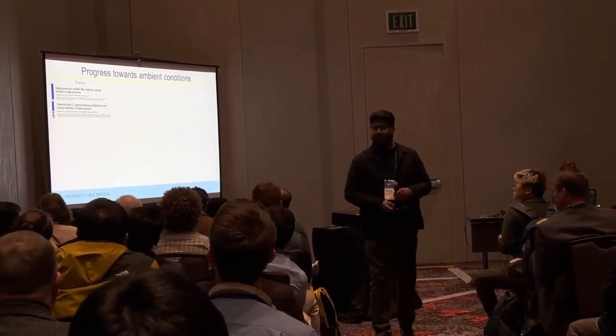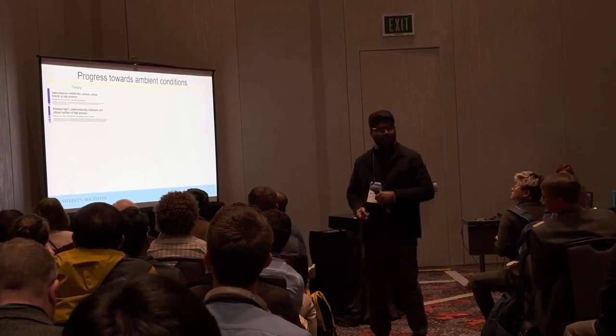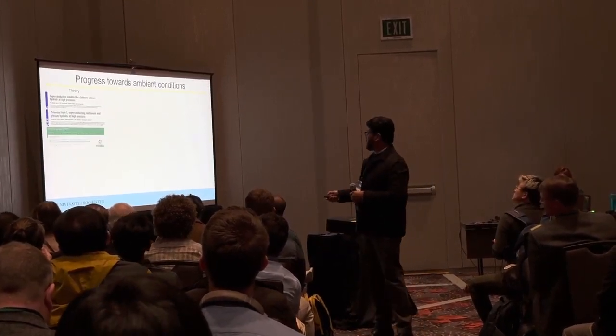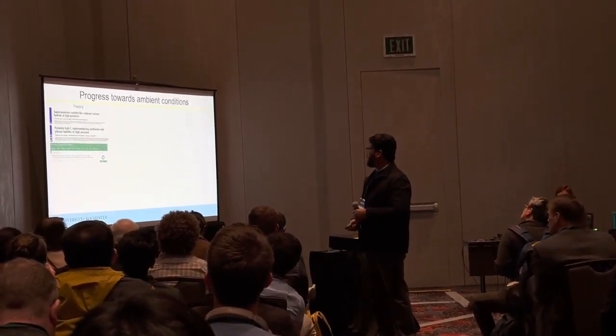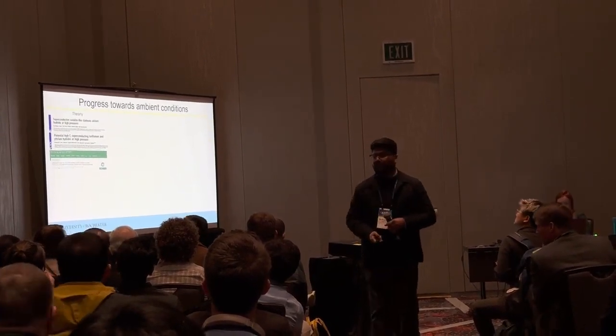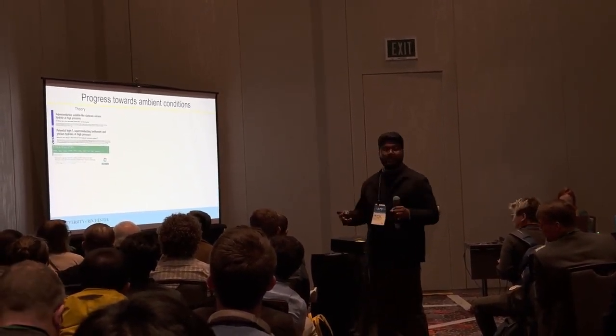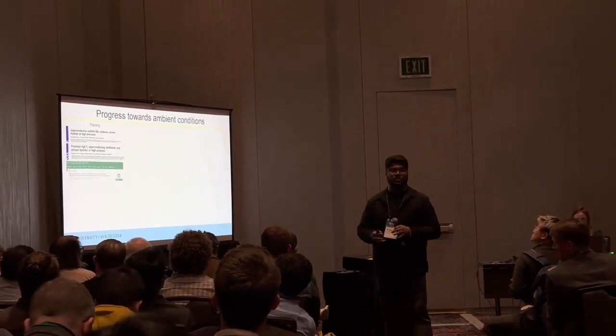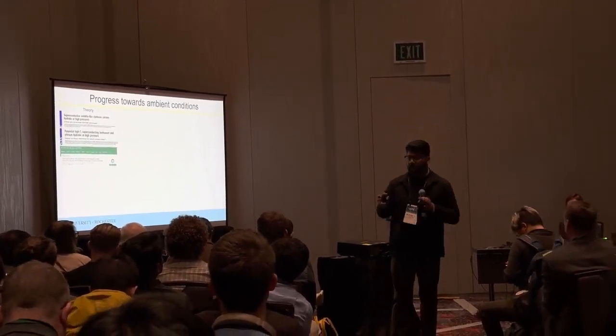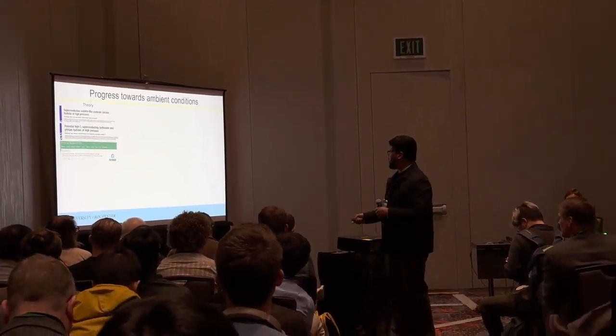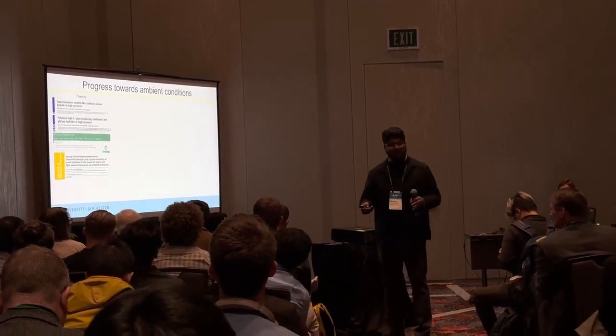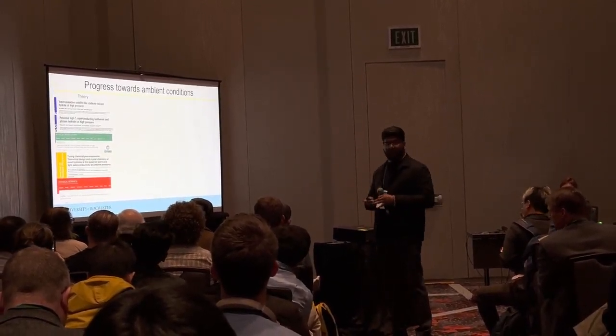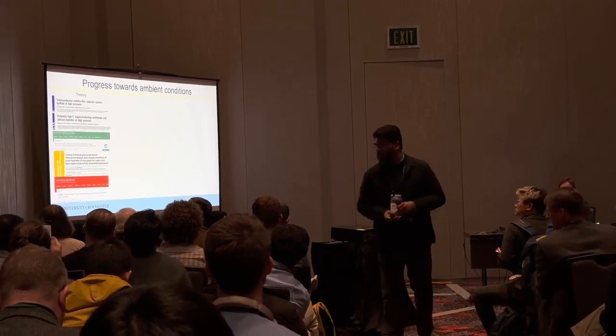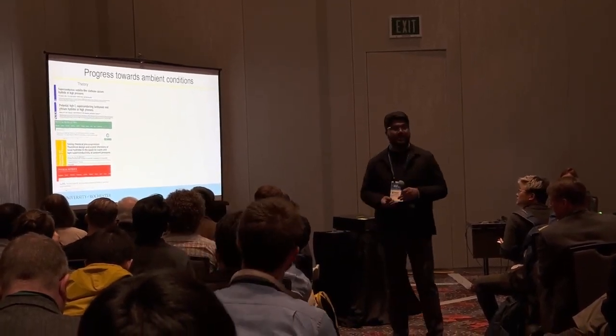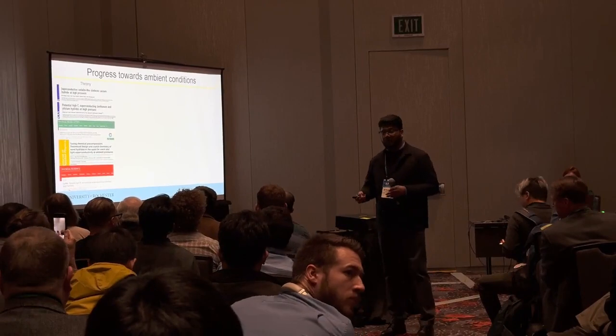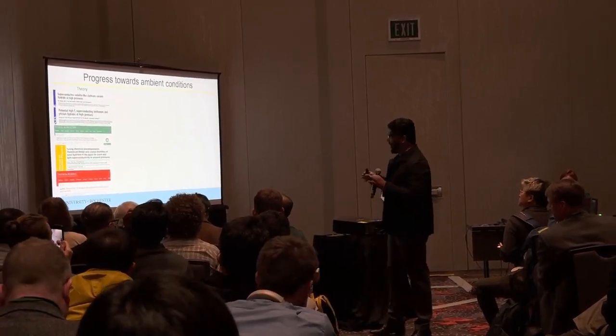And then later we see the lanthanum hydride and yttrium hydride from Russ Hemley's group, and very soon after that there was another prediction from the Cambridge group and the Yang group. Again, this rare earth metal hydride in solution to mimic the same hydrogen superconductivity at much lower pressures. Since then, there are a lot of theoretical works from the Zurich group and Ion Errea from Spain. They have studied these materials extensively, with anharmonic effects and everything. So there are a lot of theoretical works.